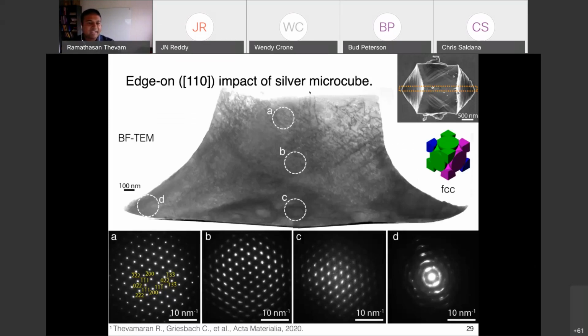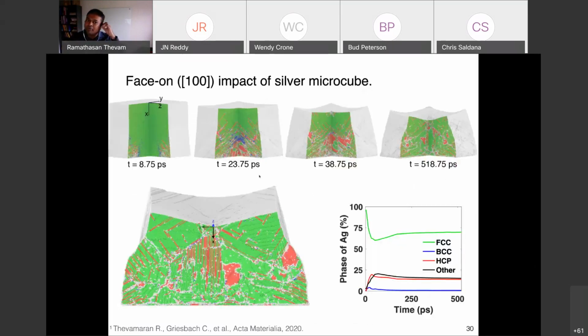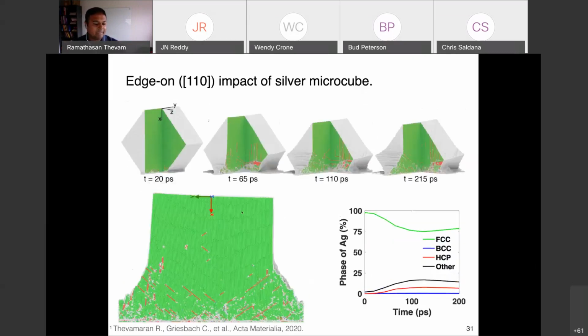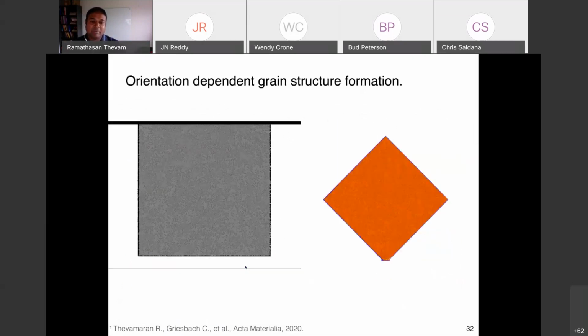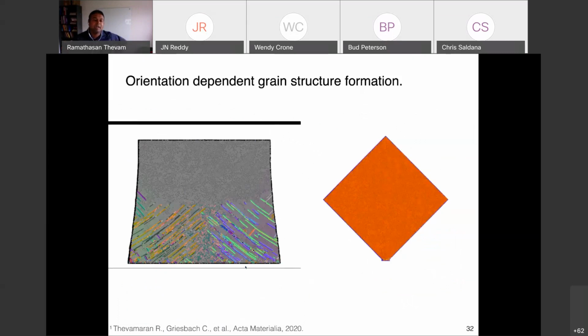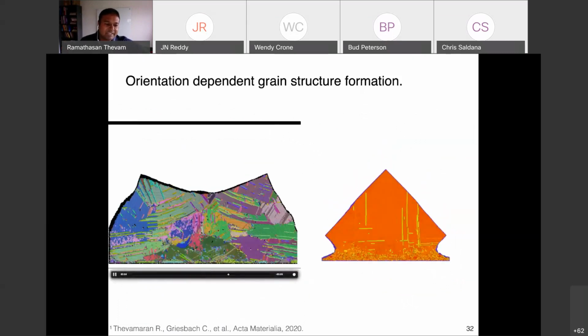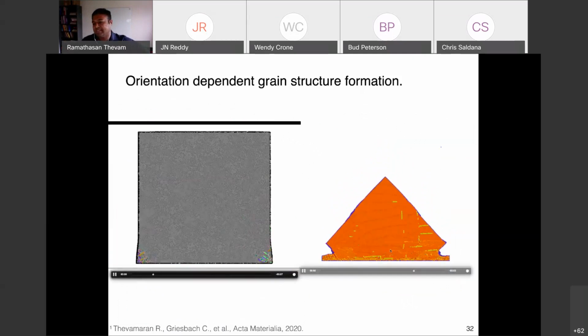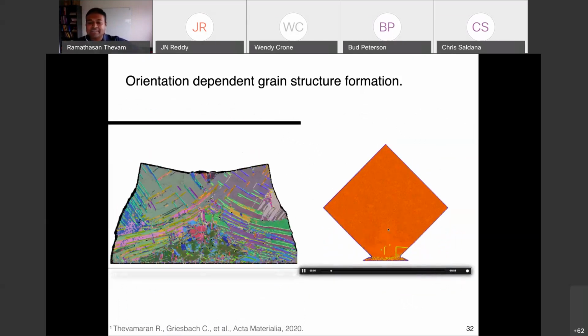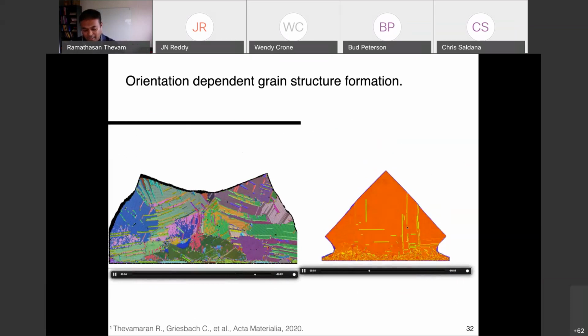To understand this further, we collaborated with Mauricio Ponga from British Columbia to do molecular dynamics simulations, which showed us the stacking faults that are created and emerge here, and then form these large hexagonal close-packed regions. This does not happen in the 110 direction of impact. The molecular dynamics simulations also show that when you impact on the face, it causes this gradient nanograin structure, whereas the corner impact or the edge impact does not cause the favorable gradient nanograin structure in the system.